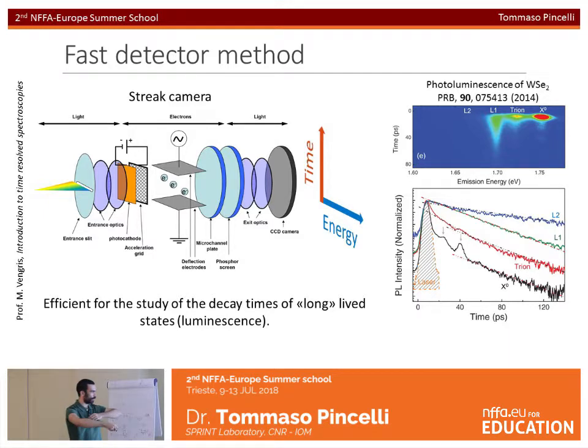Then electrons are accelerated by an acceleration grid, and then they enter the most relevant element of a streak camera, which is a pair of plates through which a very sharp voltage ramp is sent. So as the electrons enter the plates at different times, they are deviated by a different amount. Then the electrons are collected by a microchannel plate, a phosphor screen and a CCD camera. In this way, you keep the distribution of the energy along the horizontal direction, and you add the distribution in time along the vertical direction.